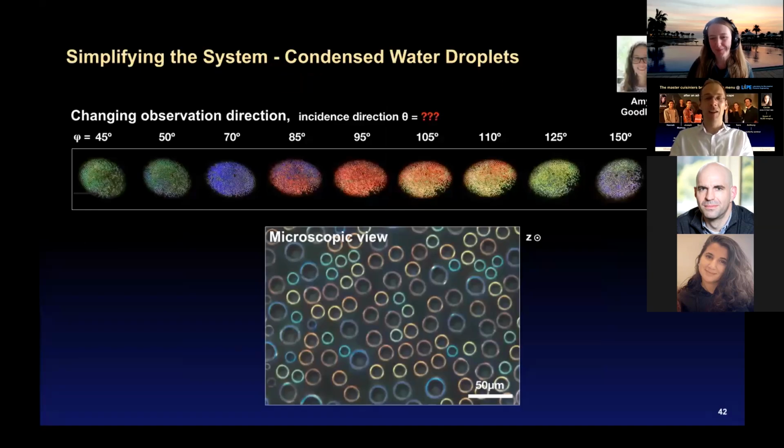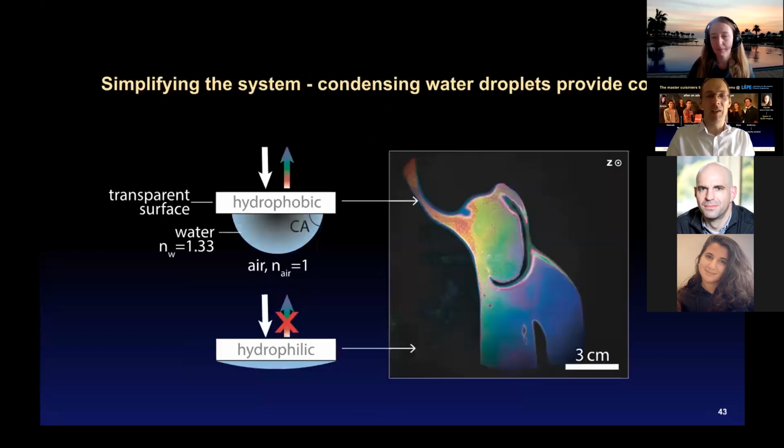All right. This works very simply in this experiment that I showed you with the condensation of droplets on the surface. You can see water droplets condensed on a PDMS surface. And you can also change whether you see colors or not just by changing the hydrophobicity of the surface. That changes the curvature of the droplet interface. And it either allows light to be in this total internal reflection interference mode, or it doesn't allow it. So you can control this.